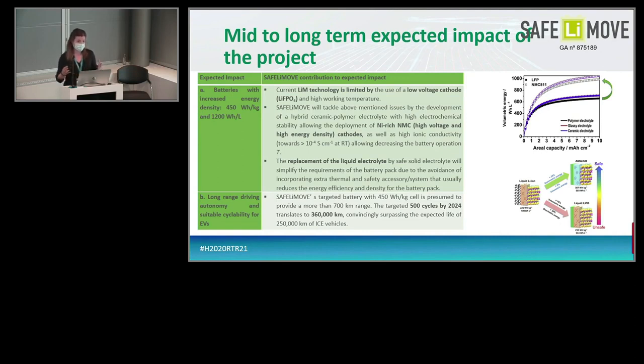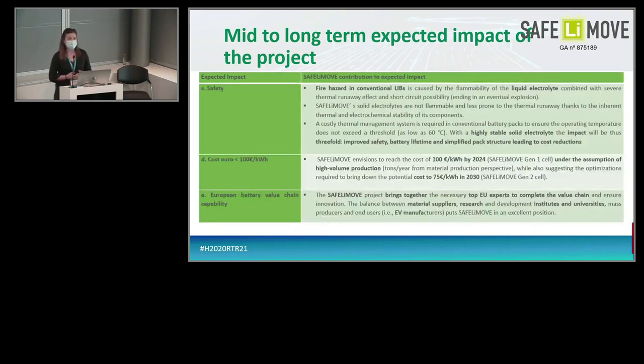Then this high energy density will have a direct impact on the driving autonomy of the car, because if we translate this 450 watt-hour per kilogram into kilometers, we may have a 700 kilometer range. And if we take into account the final target that we have for the project, that is 500 cycles, this will be translated into more than 360,000 kilometers. Then, considering the safety, as I mentioned before, and also Marta explained at the very beginning, we are looking to replace these flammable or risky liquid electrolytes with solid electrolytes.